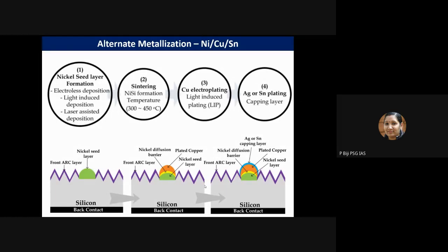In this schematic, you can see that before the nickel seed layer is deposited, you need to open up your ARC layer. The ARC layer is a silicon nitride layer. That silicon nitride layer can be opened up through wet etching using some patterning. You can do some patterning over that and then wet etching can be adopted, or you can use reactive ion etching. There are many methods to do the patterning for opening up the ARC layer.